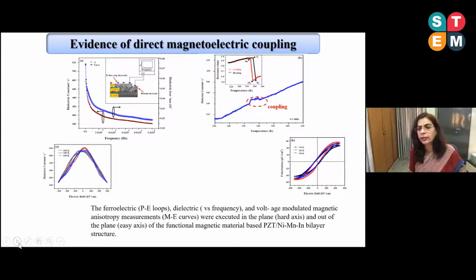We used to see a hump in the measurement of dielectric constant versus temperature, which was at a temperature near the martensite phase transformation of FSMA, nickel manganese indium. This shows that around that temperature, there was a change in the dielectric constant of the piezo layer.